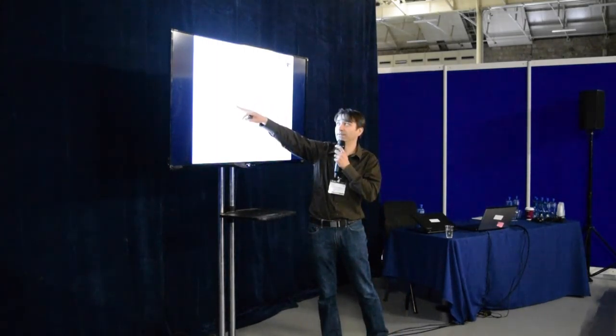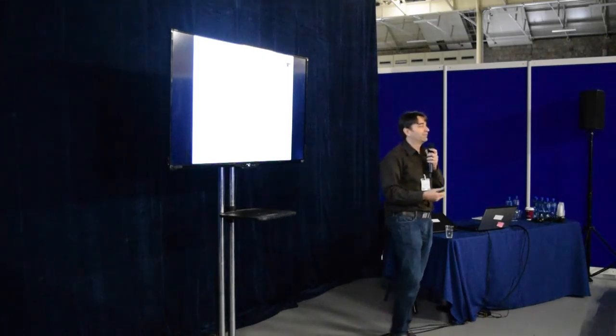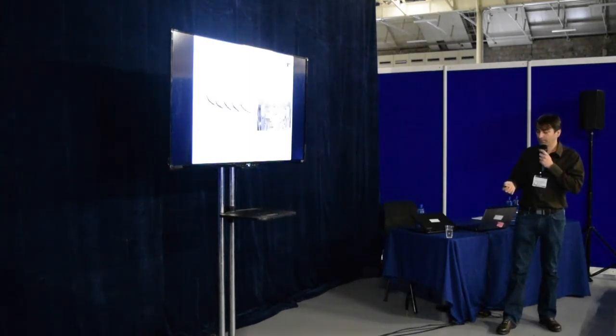So here's a simple test where we have a 2-point bend specimen, and we simply cool it down to minus 20 degrees, break it, then heat it for 2 minutes, and then it was repaired. And the process was repeated 6 times, and at 6 times we lost about 70%, and then after that about 50%. So we can repair the damage 6 times before a full repair of the pavement needs to be done.